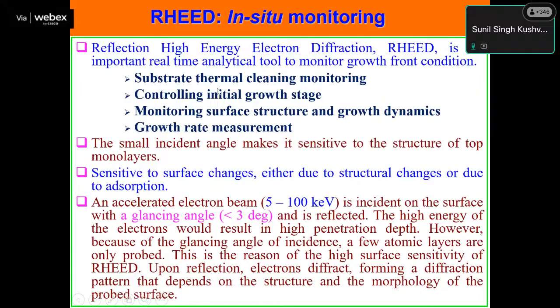What RHEED can do: we can use it for substrate thermal cleaning monitoring, because we also need to clean our substrate, not only outside using acetone, HF and other things, but also inside the chamber. We heat by thermal cleaning, basically heating up to 1000 or 850 degrees. For example, to remove silicon oxide from silicon, we have to heat to 850 degrees, because even if you clean, when loading inside the chamber, 2 to 3 nanometer silicon oxide will be there. So to remove that silicon oxide, we have to clean inside the vacuum, at 850 degrees in the UHV, and then we are able to see silicon oxide free silicon. Then again, you can monitor using the RHEED.